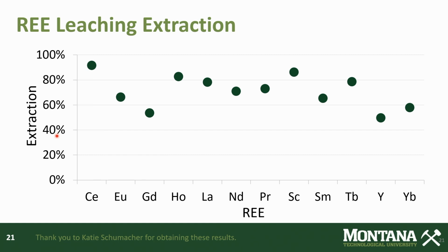Now, last couple of points on this. If you look at the cerium in the first element there, that's the highest concentration in this particular sample. It's present at about 10% in the sample we've got. So that's really the most representative of the extraction efficiencies. Some of these other elements are present at well under 1%. So you can appreciate if you've got a residual of maybe 0.04, 0.02%, you're going to show a little bit lower extraction efficiency than you had a higher concentrate grade. So that's the reason for the variability in the extraction efficiencies.